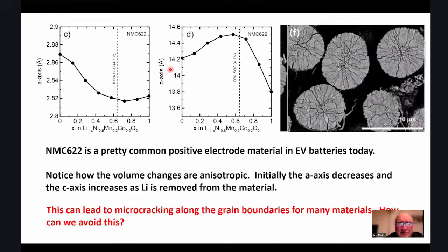And what can happen because of this is, because these NMC particles are made up of all these subparticles, and they can be aligned more or less at random, because the expansion is anisotropic, you can develop cracks along the grain boundaries that you see here, okay? So what is the impact of these cracks, and then ultimately, how can we avoid them?